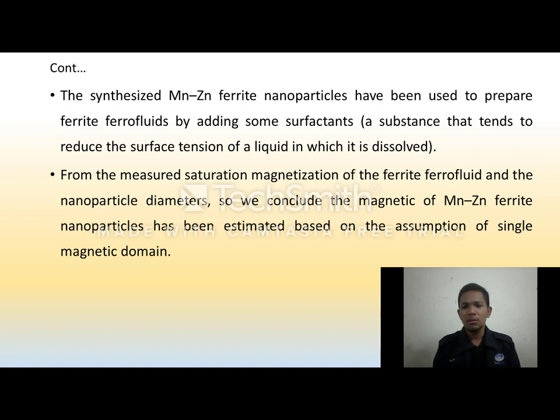From the measured saturation magnetization of the ferrite fluid and the nanoparticle diameter, we conclude the magnetic moment of manganese zinc ferrite nanoparticles has been estimated based on the assumption of a single magnetic domain.